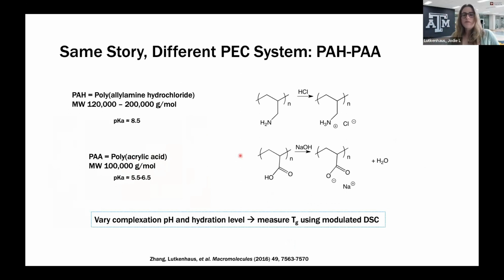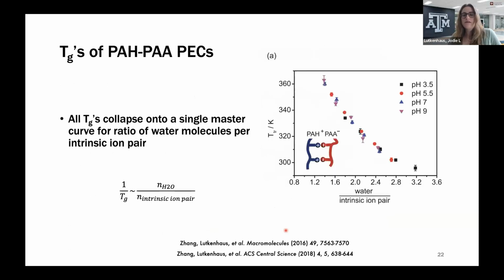Okay, so we know that that relationship holds true for one system at all these different salt concentrations. But what about another system? This is a different system that is very sensitive to pH. So we have polyallylamine and polyacrylic acid, and they have the corresponding pKa's here. So we can make complexes with them at varying pH, and we can change the water content and measure the Tg just as before. And here's the result. So this says TTR, like a thermal transition, but it's really a Tg. So this is the glass transition versus the water to intrinsic ion pairing ratio for all the different pH values of assembly. Again, they collapse onto a single curve with no adjustable parameters. So it's following the same relationship as this different system.